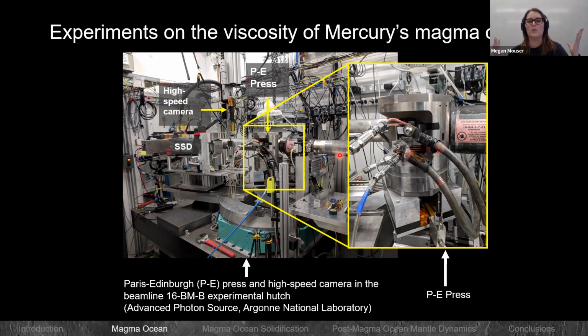What's so great about this particular setup is that we can utilize the X-ray source at the beamline. And we have this high-speed camera over here that we could lower down. Once we turn the beam on, we can actually image inside of the experiment as it's happening, which is really cool because I think as experimental petrologists, we put something in and kind of hope for the best and then see how it looks when it comes out. In this case, you can really see how it's happening during the process, which is really fun to do. So we get our experiment in there, we get it up to our desired pressure, which we were testing between 1 and 6 GPa, things that are relevant for Mercury.